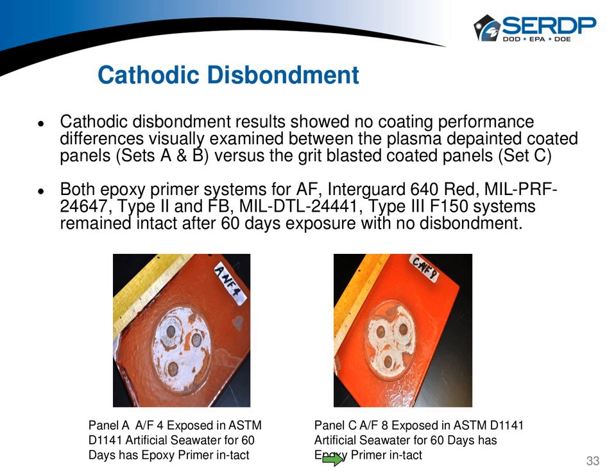Okay, if any of the tests, and this is my personal, professional opinion, would have shown some problem with that oxide at the surface, I felt that cathodic delamination would have done so. And the reason for that is it's an electrochemical test, which is going to tend to find weaknesses in that oxide layer. And in fact, we didn't find any of those problems.